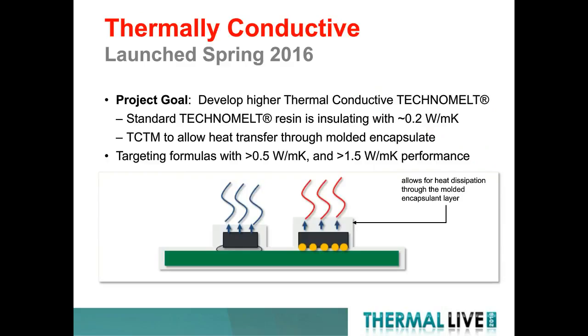The project goal we endeavored down was to develop a higher thermally conductive material. As I mentioned before, with 0.2 watts per meter-K, you really don't transfer much heat. The thermally conductive Technomelt allows heat transfer through that molded encapsulating layer. Our first generation material is over half a watt per meter-K. It's actually measuring at about 0.6, 0.7. Our goal is to develop a material roadmap with materials up to 1.5 watts per meter-K for more power electronics-centric type